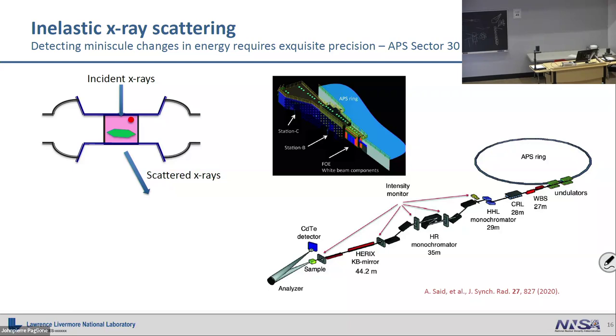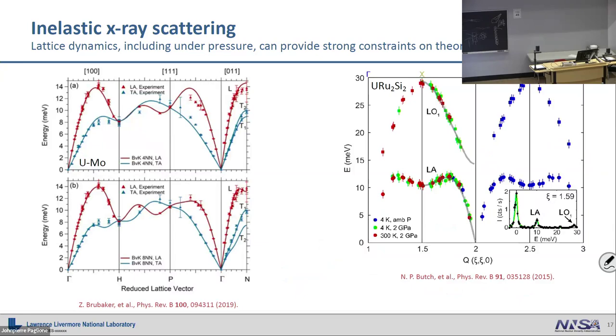But again, you can throw away a lot of X-rays at a synchrotron, throw away a lot of photons. So you put your sample in there, and there's this very long analyzer. It's the same way: X-rays come in a diamond, come out the other diamond, and the scattered X-rays go through an analyzer crystal and then get bounced over, so you get your energy dependent and your spatial dependent answers so you can find the inelastic component.